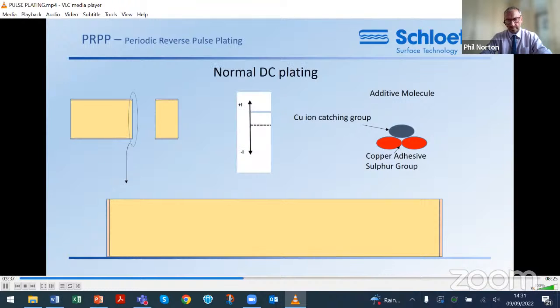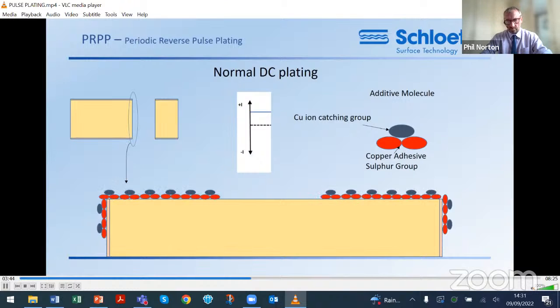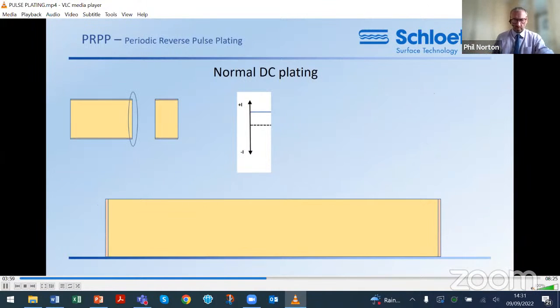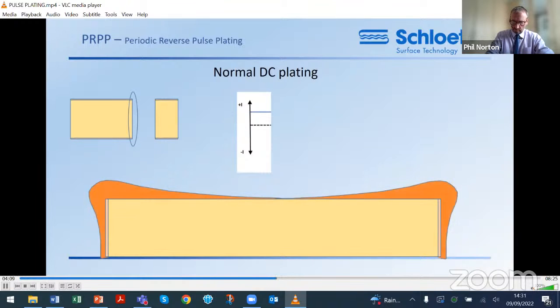During normal DC plating, where the current is always positive, the additive molecules arrange themselves at the substrate surface. The sulfur groups help the molecule to stay on the copper surface, and the other part of the molecule helps to attract copper to the surface from the electrolyte. This maintains the efficiency of the plating reaction. However, this arrangement is so efficient it is very susceptible to current density variation, and in this exaggerated example gives rise to typical and associated variation in copper thickness.